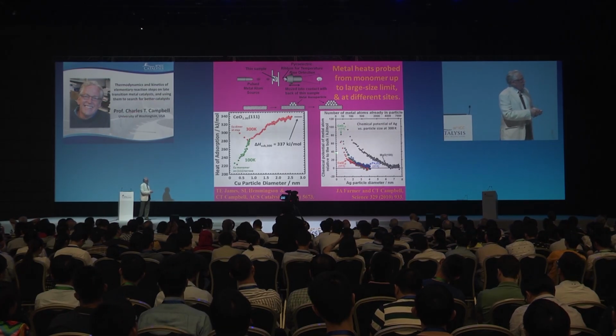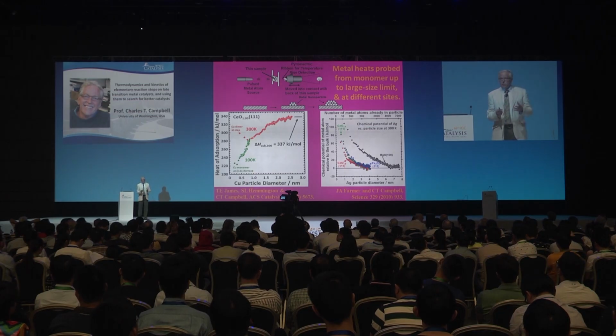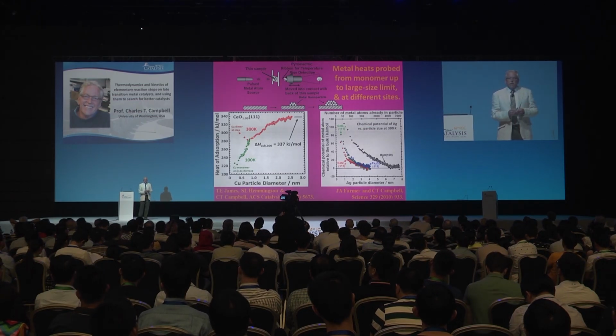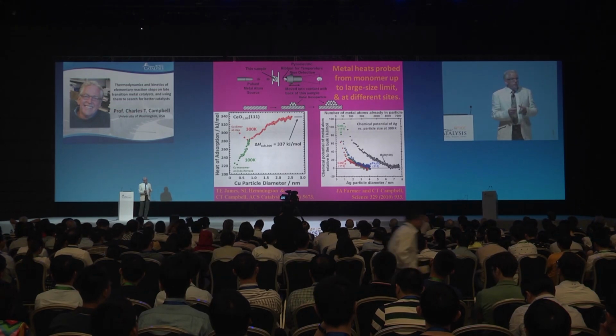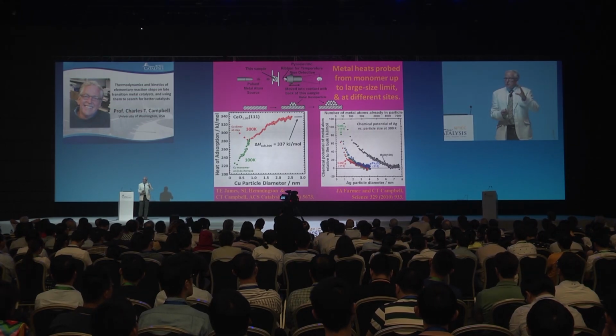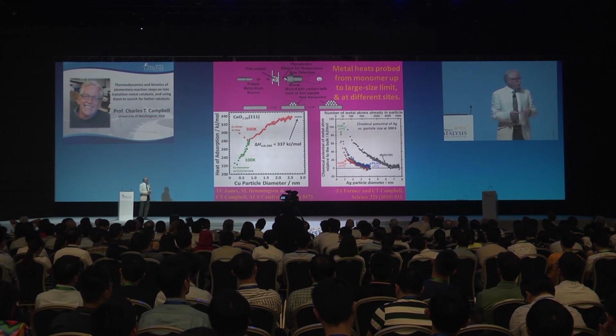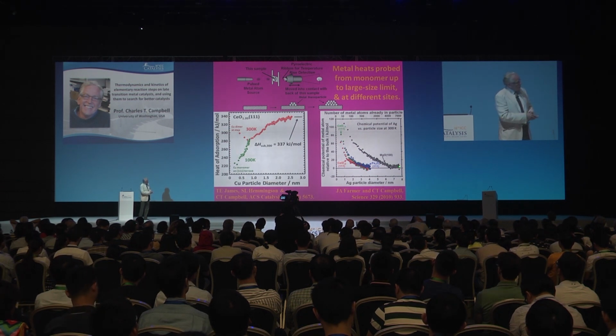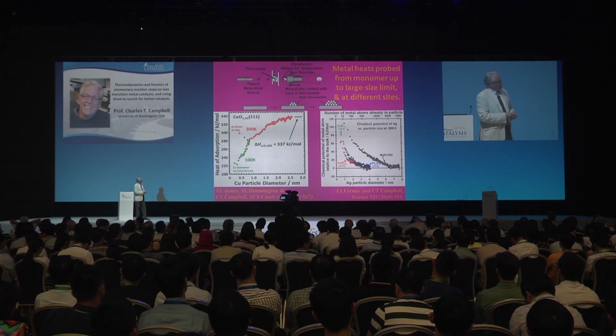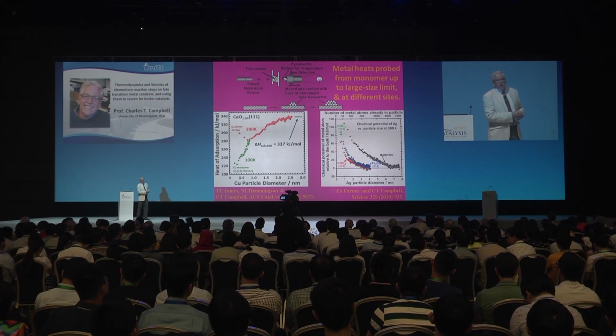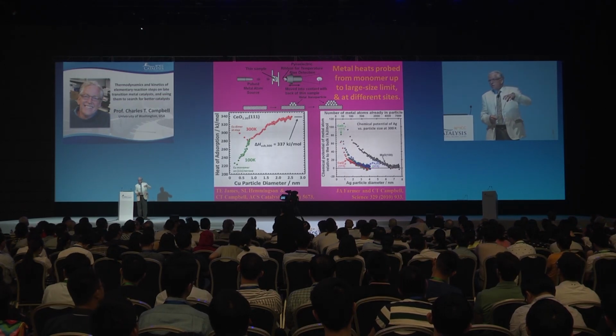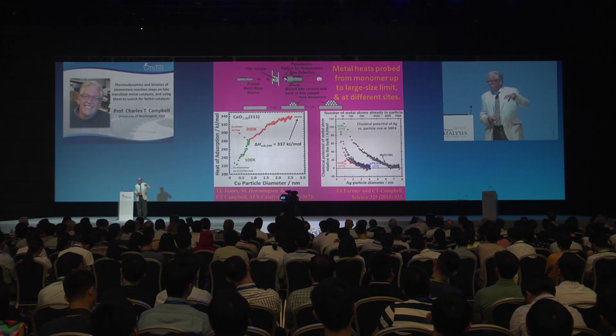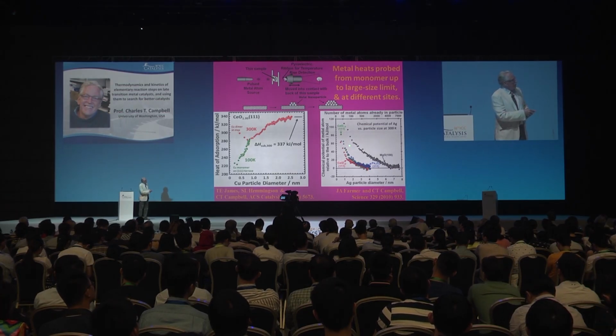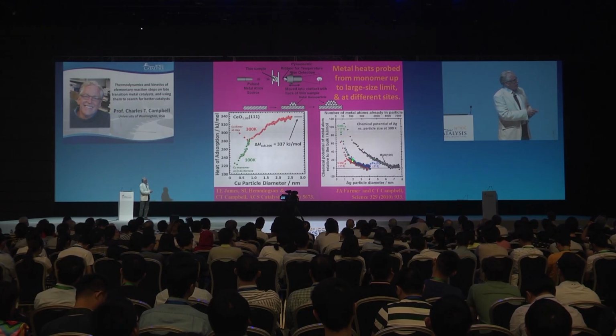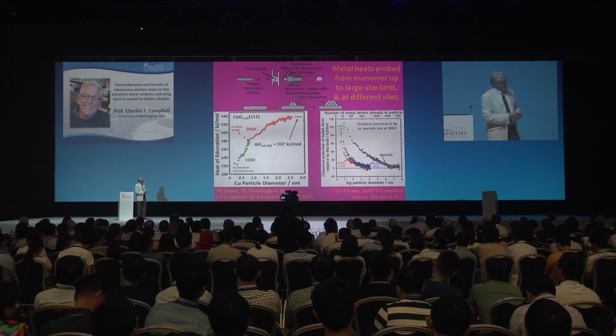And I'm not going to talk about the results of that today, but there are many examples where we and others have found that the adsorption energies of small species like oxygen and CO are stronger, as evidenced from temperature-programmed desorption, on smaller particles than they are on larger particles. But there's a secondary effect, and that is that the chemical potential decreases the more strongly the cluster binds to the oxide support. So you can also tune the chemical reactivity for the same cluster size by tuning the nature of the support material upon which it's attached.